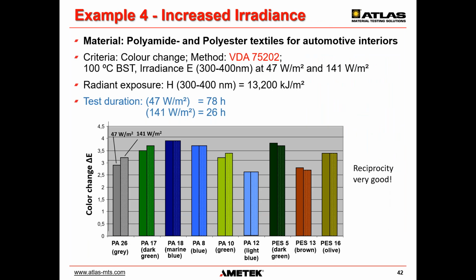Here's a fourth example, this time for two different types of automotive interior textiles. Test 1 uses a relatively normal irradiance level of 47 watt per square meter, and test 2 3 times the irradiance, 141 watt per square meter. As you can see from the graph, the reciprocity was quite good. Now, one thing to note here.